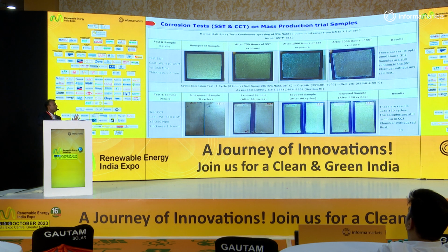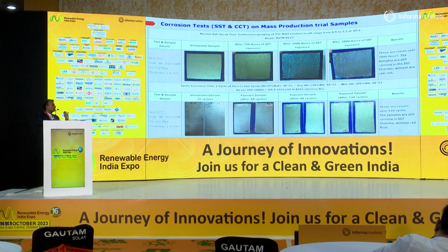It has crossed 2000 hours of SST without any red rust, and the samples are still running in the SST chamber. In case of CCT, it has crossed 120 cycles. One cycle consists of 8 hours, in which 2 hours is a continuous salt spray, then drying for 4 hours at 60 degrees Celsius, and then again wetting, where it maintains 95% relative humidity.